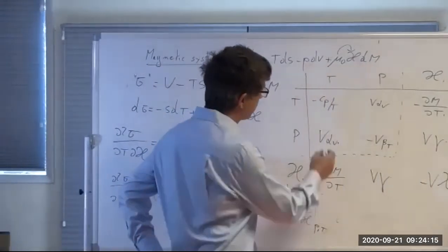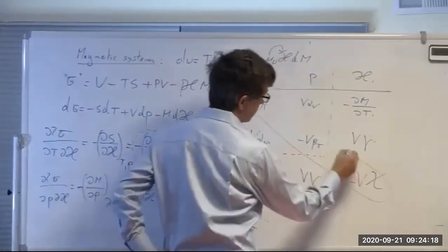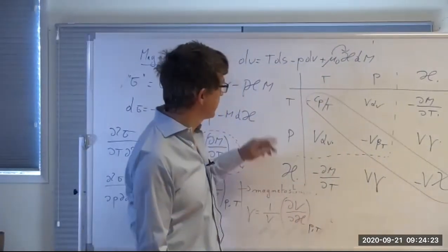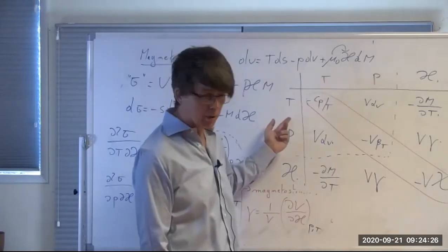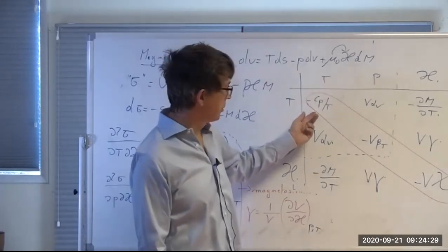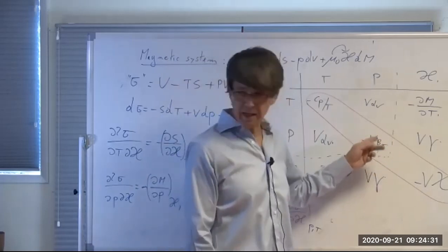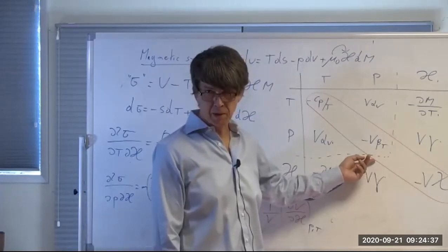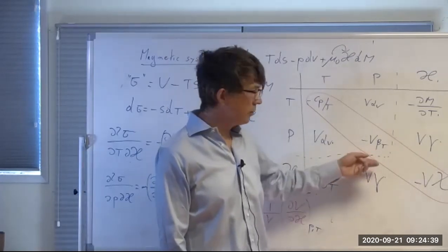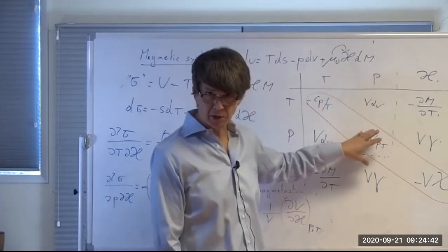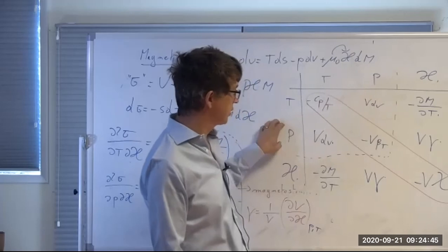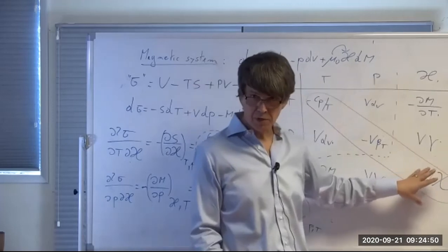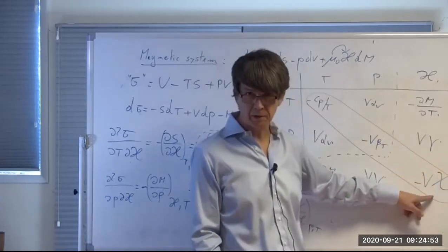So if you look at the diagonal elements, they are the properties that live within one field, right? Because they are the second derivatives with respect to twice the same variable. So heat capacity comes out of thermal science. This is some mechanical variable. In our case, it's compressibility because we treat our system isotropically. But in general, you could have a whole submatrix here of elastic constants, right? Because this is mechanics with mechanics. This is magnetism with magnetism. So that gives you the intrinsic property of electromagnetism, which is susceptibility.